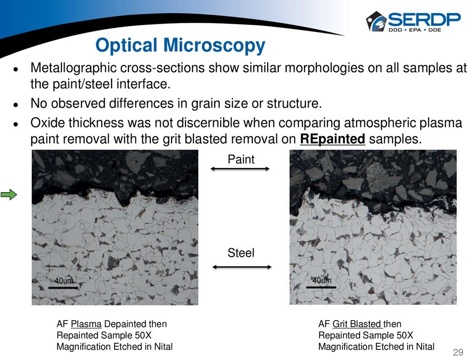So these are optical micrographs taken from cross-sections showing the paint-steel interface, and they were etched with nital to bring out the grain boundaries of the steel. And notice, based on the scale, where's the scale? 40 micron here. So again, the roughness of these surfaces is on the order of 50 microns in scale. We're looking for an oxide that is less than a micron, and it's pretty tough to see that in these. I think we'd have to do some pretty fancy techniques to really look for that. But the point of these two samples is that on all the ones that we looked at, we couldn't find any differences, whether it was grit blasted or plasma treated.